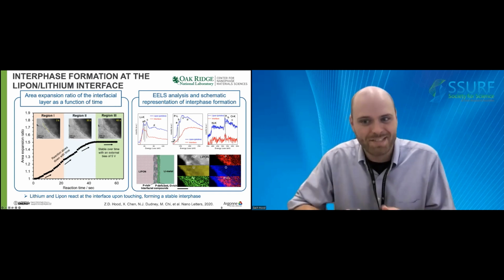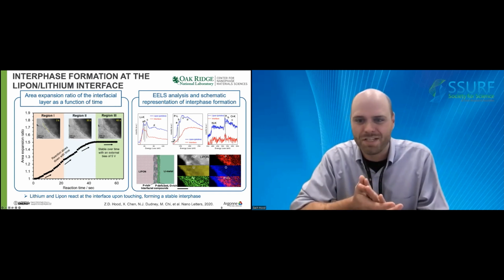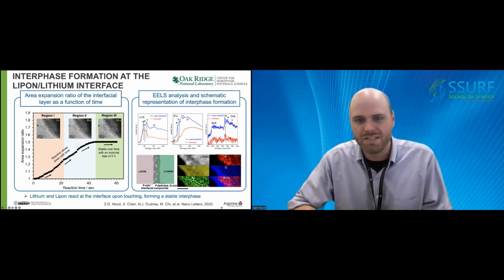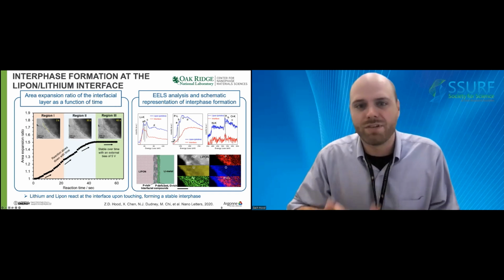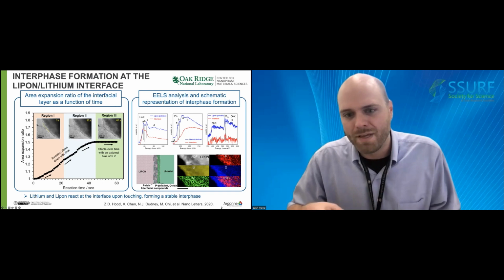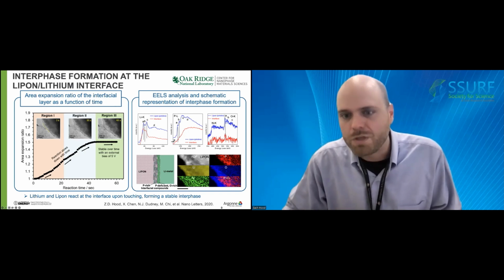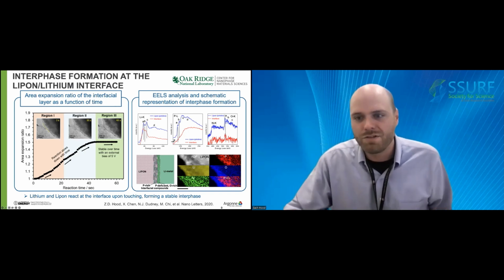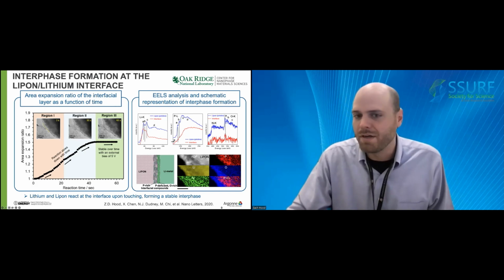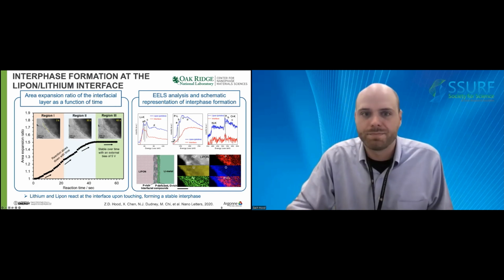Furthermore, this interface contains a high concentration of phases with high lithium ionic conductivity, such as lithium nitride, lithium phosphide, and several other phases, which may explain the good interfacial conductance of the LiPON lithium interface.